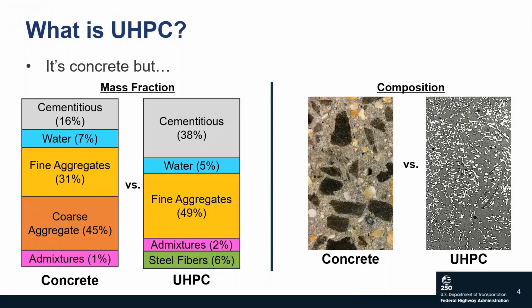So the image you see here represents the composition of conventional concrete and UHPC based on mass percentages. As you see, UHPC has a higher percentage of cementitious materials. It does not contain coarse aggregates, so you'll see only very fine aggregate or fillers in UHPC. It has a very low water to cement ratio, about 0.2 typically, and it contains short steel fibers.